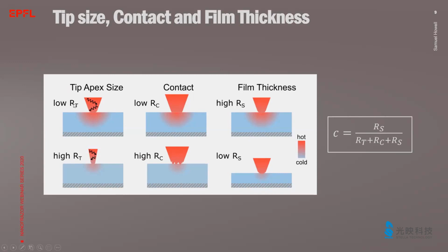The consequence is that with a blunt tip, higher temperatures can be achieved than with a sharp tip. But in TSPL, to reach high resolution, a sharp tip is often required. For those who have worked with the NanoFrazor, this effect can be experienced when blunt tips are used, which are typically good to write deeper patterns or larger areas.